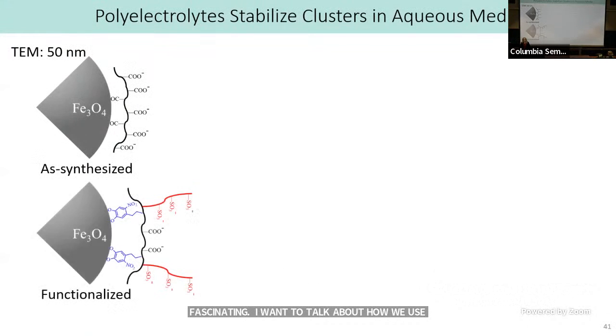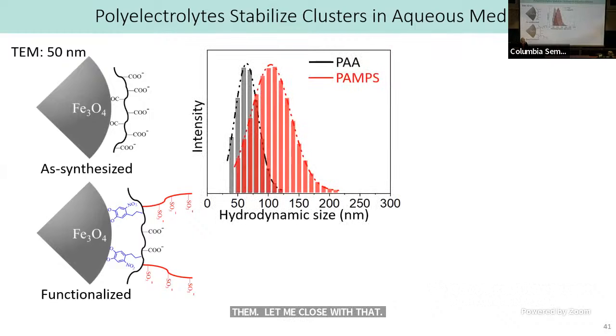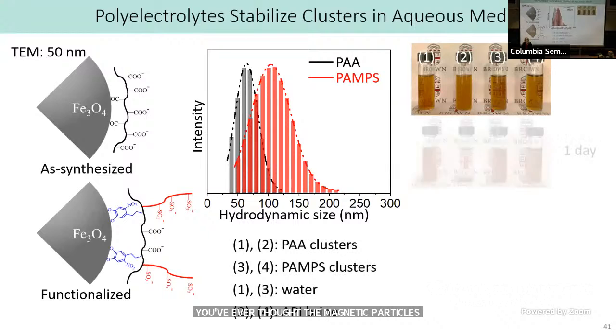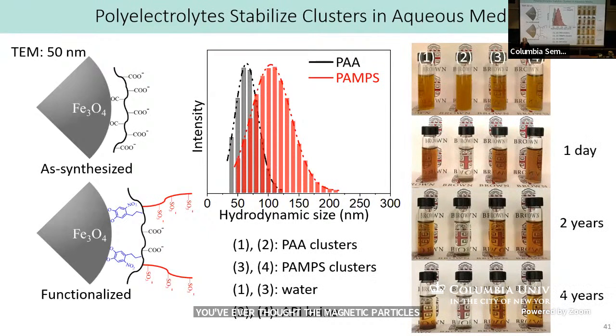So the first thing you can do with these is, if you've ever thought that magnetic particles will aggregate, well, they do. I just showed you some that do, but you can totally coat them so they don't aggregate. Over on the right, these are what the clusters look like in solution. They can be freeze dried, but then you can dissolve them in whatever you want. And they have a polymer coating that has taken several student lifetimes in different ways to optimize. What you're looking at are solutions that are in brine. Some of these solutions are seawater.